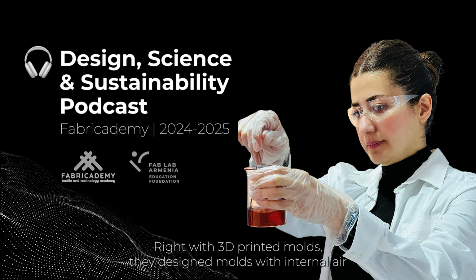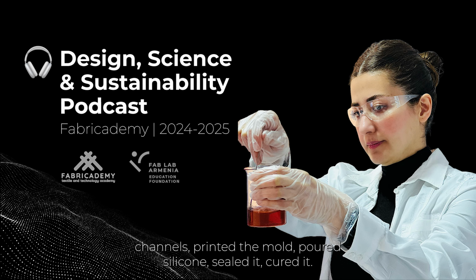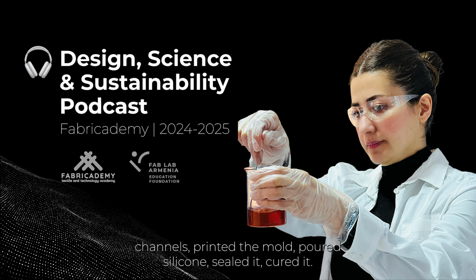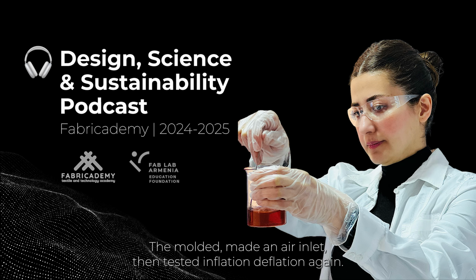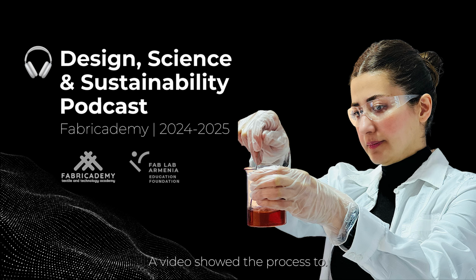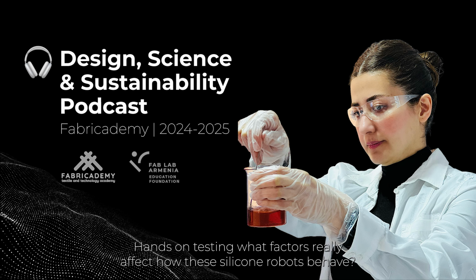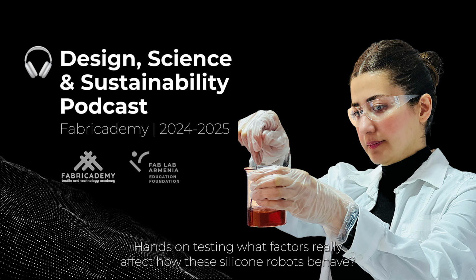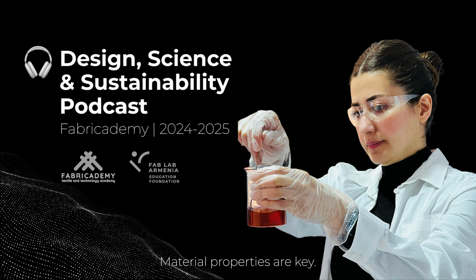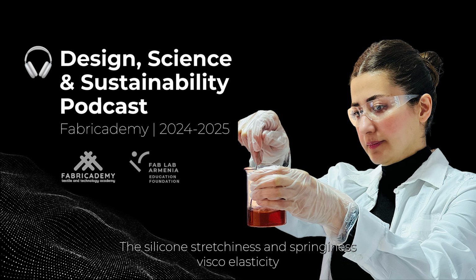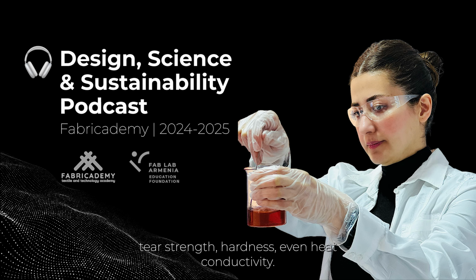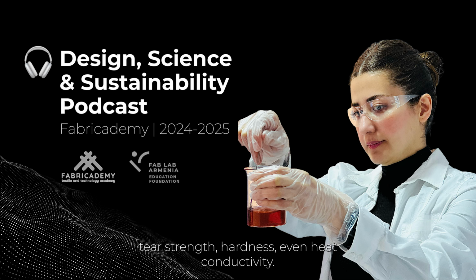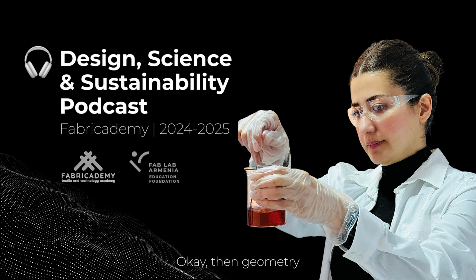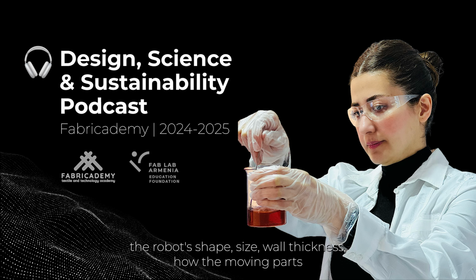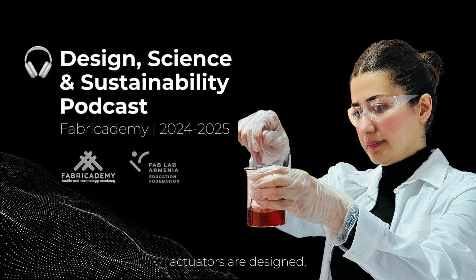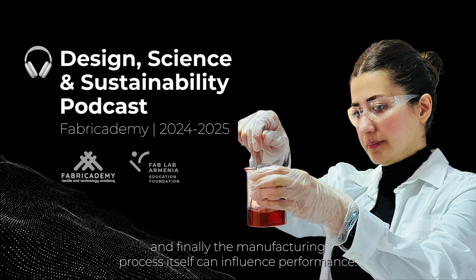Right. With 3D printed molds, they designed molds with internal air channels. Printed the mold, poured silicone, sealed it, cured it, demolded, made an air inlet, then tested inflation, deflation again. A video showed the process too. Hands-on testing. What factors really affect how these silicone robots behave? Material properties are key. The silicone's stretchiness and springiness, viscoelasticity, tear strength, hardness, even heat conductivity. Then geometry. The robot's shape, size, wall thickness, how the moving parts, actuators, are designed, and finally, the manufacturing process itself can influence performance.